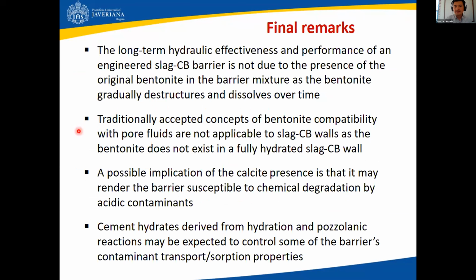Having said that, we believe that the traditionally accepted concepts of compatibility that are normally applicable for soil-bentonite barriers are not applicable to slag-CB barriers, or in fact to cement-bentonite barriers, because the bentonite does not exist in a fully hydrated slag-CB wall. To us, a possible implication of the calcite presence is that it may render the barrier vulnerable or susceptible to chemical degradation if the contaminants are acidic.